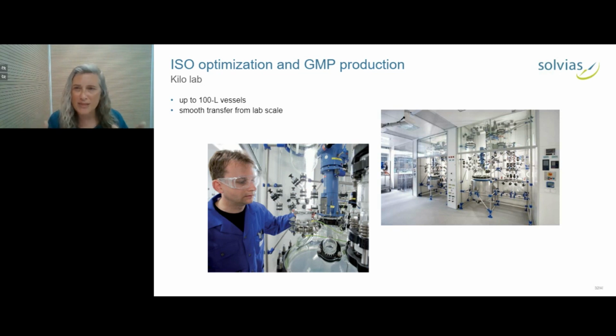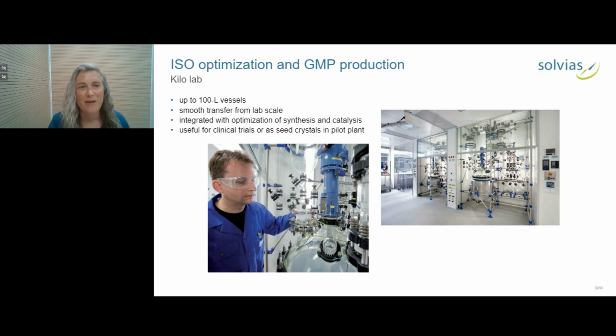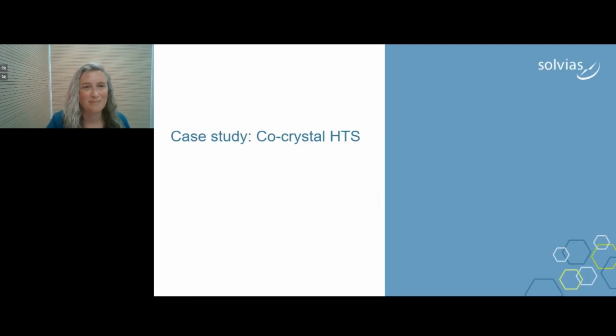And we can really do a smooth transfer of what we learn from the crystallization optimization on the small scale to the larger scale. And this can be directly integrated into an optimization and development of a synthesis and perhaps a catalyzed synthetic process. So that not only do you get the right material with the right purity, but you also get it in the right solid form. And the GMP material on the kilogram scale can be used for clinical trials with humans, or for instance, as seed crystals in a pilot plant.